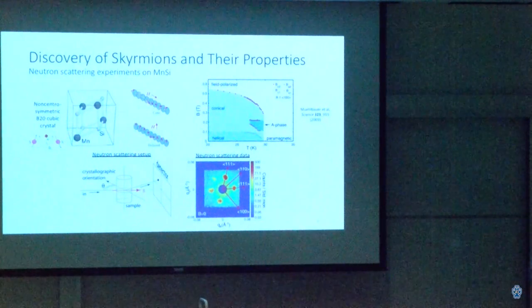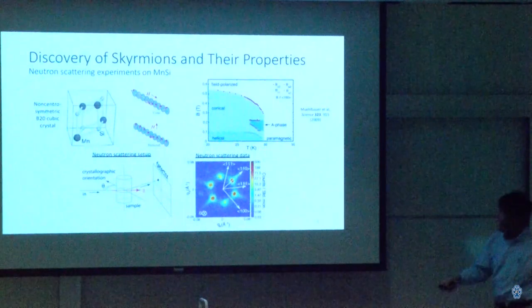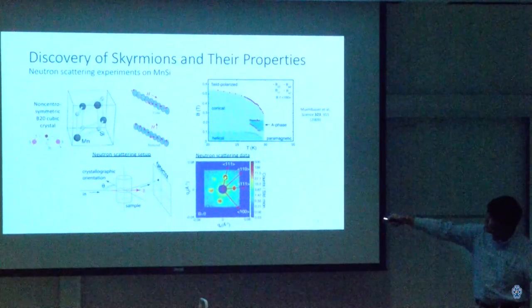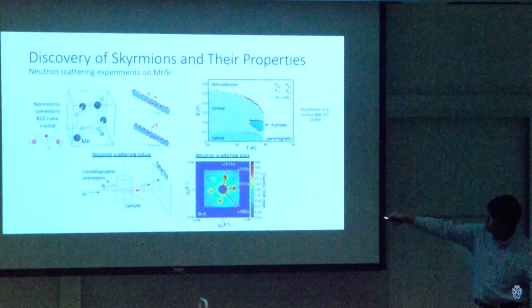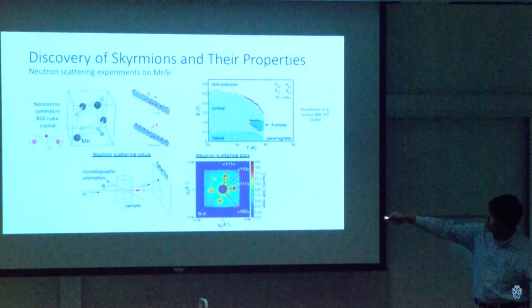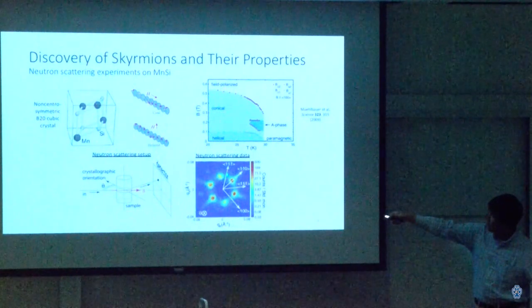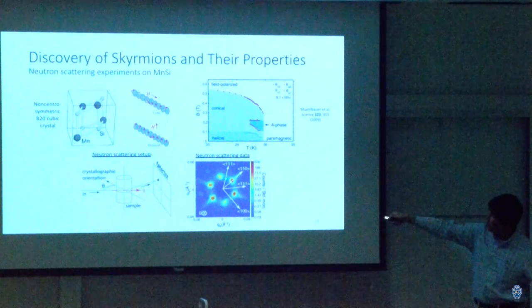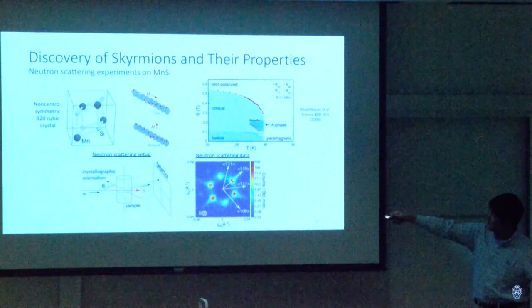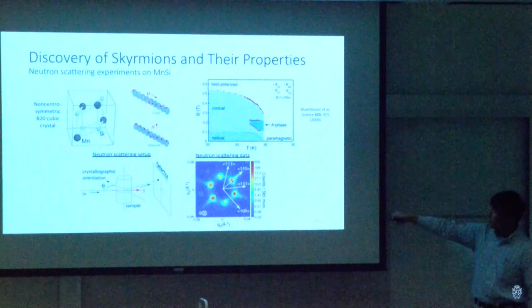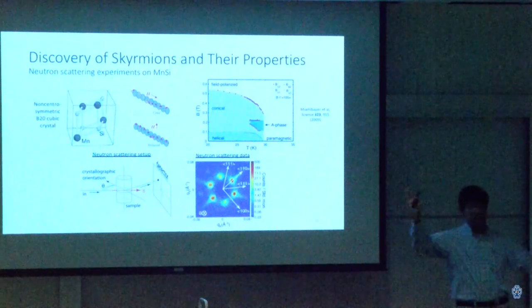As they warm the system up, from the helical through the conical into the A phase, however, something happened. Note where this peak is. It's along the so-called 1-1-1 direction. Here's the 1-1-1 direction. Then as soon as they go into the A phase, there's not a peak anymore. Instead, there are six peaks, and they all seem to be shifted.